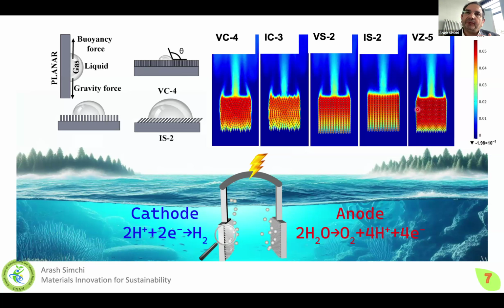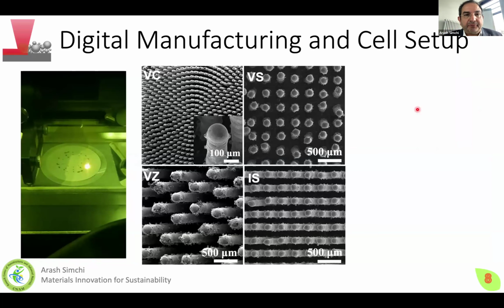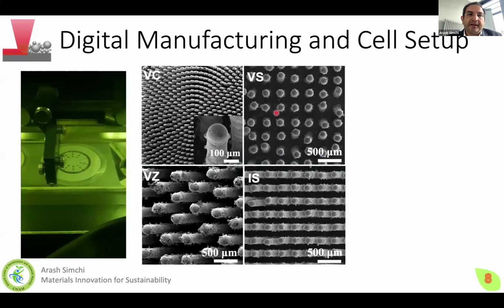By design, we can change the gas evolution reaction kinetics. After knowing that, we went to the laboratory. We use additive manufacturing technologies to prepare such electrodes by laser melting of powders, as you know, LPBF, one of the most used techniques, as you see in the film. We produced such structures with different distances, with different alignments.